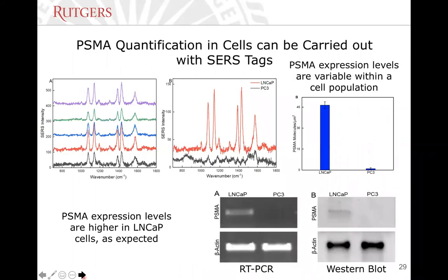And so we started, first of all, to monitor the expression of the PSMA biomarker on cells. And we use 2 cell lines. We have the LNCaP cell line, which is known to express high numbers of PSMA, compared to the PC3 cell line, which is shown to not express much PSMA. And this is known from the literature, but we obviously had to verify it. We verified it using RT-PCR and Western blotting. And we saw that exactly is what we found, that in LNCaP, we have expression of PSMA using both tests, whereas in PC3, we have basically no expression detectable.